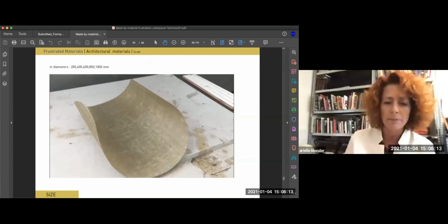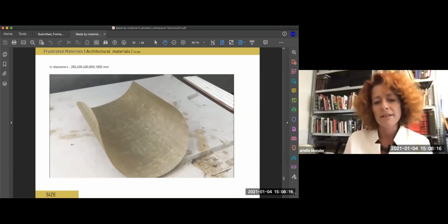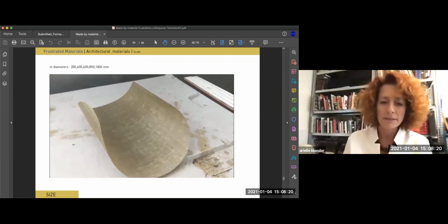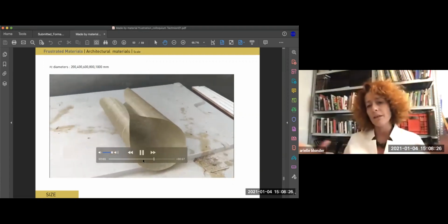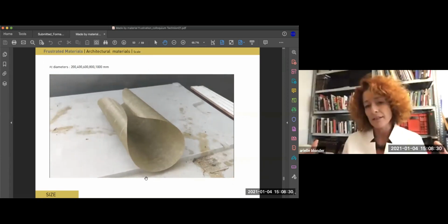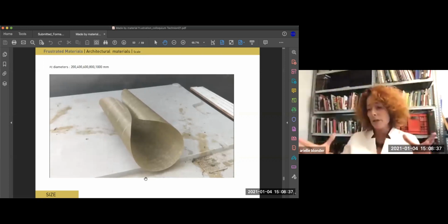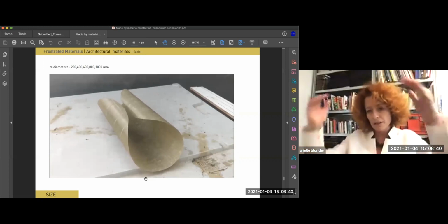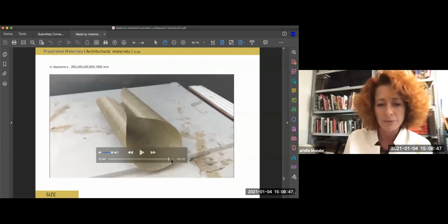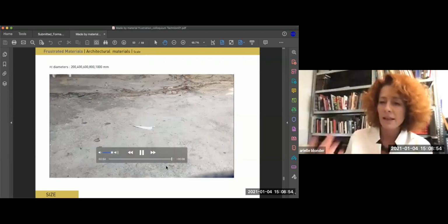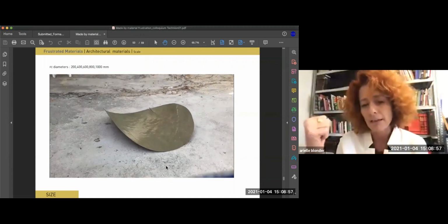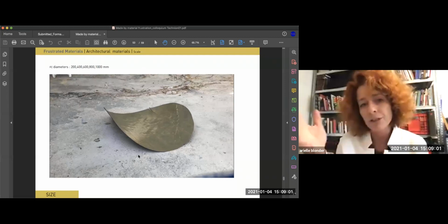I don't know why this is slowed down. I'll speed it up a bit, but this whole process takes about a minute or two. Now what we see here is actually interesting. We enlarged the size, but curvature remains the same because it was not a parameter in our very simple equation. So radius remains the same, and what happens when the disk grows bigger, it just continues to close the shape. And we'll talk about it if I have some more time when we deal with scaling. Here we have a disk of the same size, but this time with increased, scaled thickness. So shape would remain the same as we had before, but radius of curvature would differ.